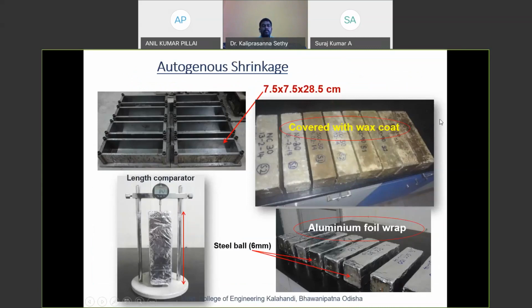So here this is the autogenous shrinkage. As you know, autogenous shrinkage is nothing but the uniform reduction of internal water due to hydration of cement when it contacts with water. This is particularly considerable in the case of high strength concrete, where we use more quantity of cement. Since we are trying to develop high strength concretes like 60, 90 and 100 MPa, we planned for this autogenous shrinkage test.